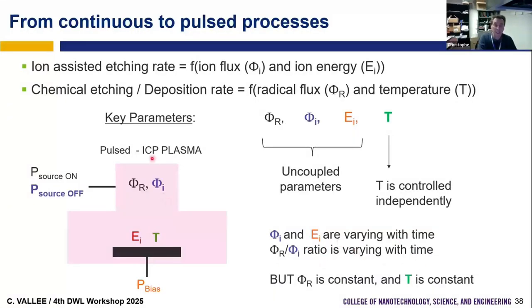And this is yes, if we start, for example, to pulse the plasma, it means that we don't have a continuous wave. So now plasma is sometimes on, plasma is sometimes off. So the power we apply to the source, sometimes we apply, for example, 500 watts, then we stop to apply the power. Then we apply again 500 watts, and we stop to apply the power. So we pulse the plasma source. And if we pulse, we can change the plasma properties with time. And if we change the plasma properties with time, we can modulate depending on the frequency.